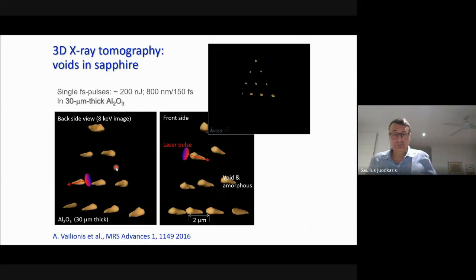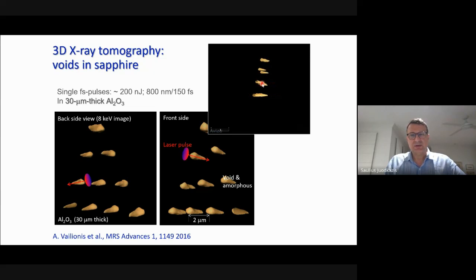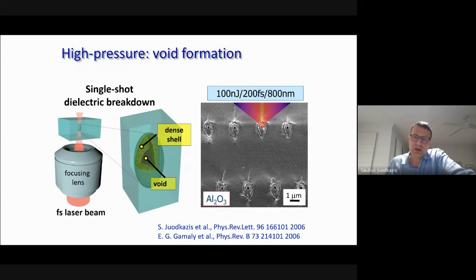And here is an example of those first experiments. We took sapphire, we polished it very thin in order to make those tomography images, and then a single femtosecond laser pulse was modifying those micro volumes along propagation. Now, if you look inside, let's appreciate those 3D renderings of those images. So they are inside. They are modifications of single shots. Resolution was not showing what is inside, but this is shown here. If we break the sample, we will recognize that in the middle of the sample, and this is a real surface, just below the surface at a couple of microns, this is the focusing cone of tightly focused light. We are pinching a hole inside sapphire.